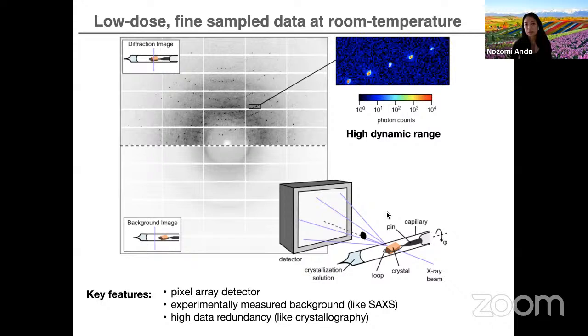We can do that with a pixel array detector because of the high dynamic range as well as the fast frame rate. And that allows us to generate a data set that is large and has a lot of data redundancy. And then we can utilize some of the strategies from crystallographic refinement that leverage that redundancy information. And I'll just mention too that all of our experiments were done at room temperature. So the data I will show you today is a room temperature data set.